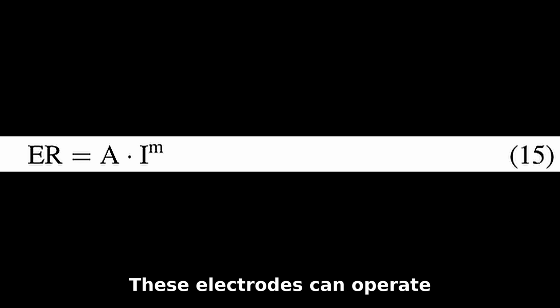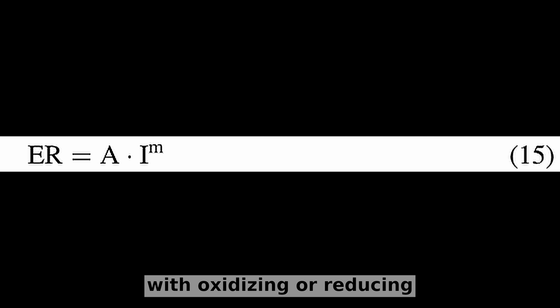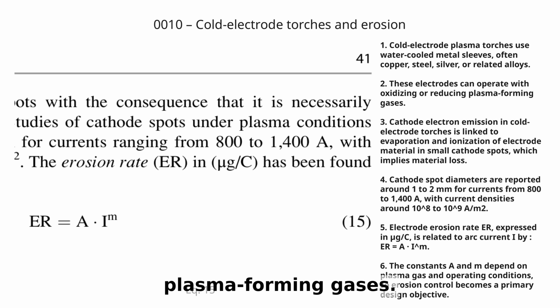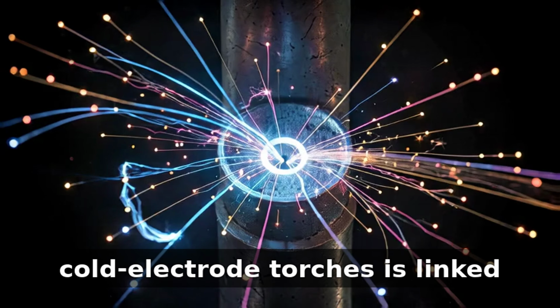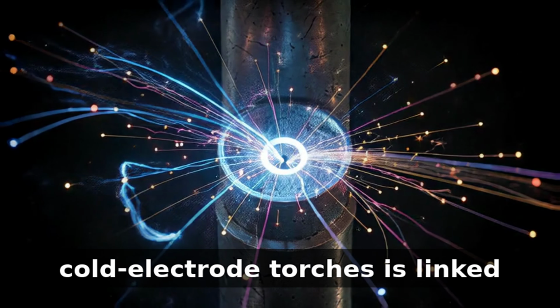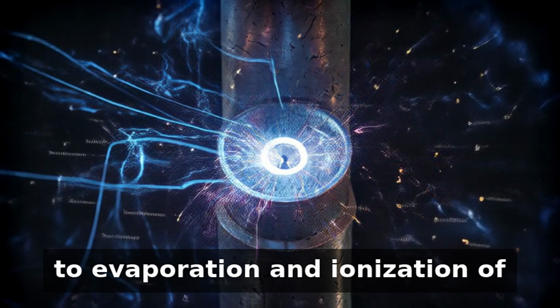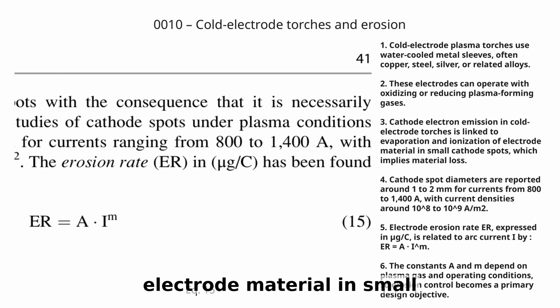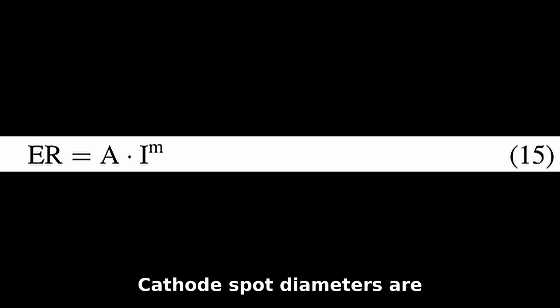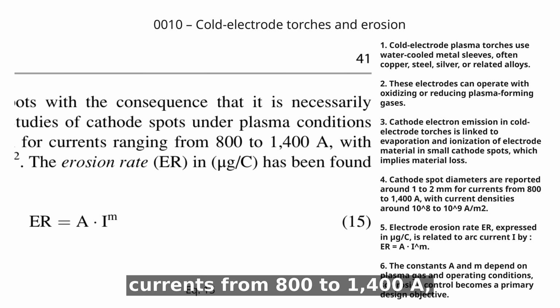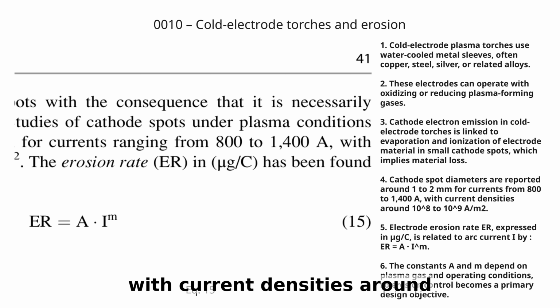These electrodes can operate with oxidizing or reducing plasma-forming gases. Cathode electron emission in cold-electrode torches is linked to evaporation and ionization of electrode material in small cathode spots, which implies material loss. Cathode spot diameters are reported around 1 to 2 millimeters for currents from 800 to 1400 A, with current densities around 10^8 to 10^9 amperes per square meter.